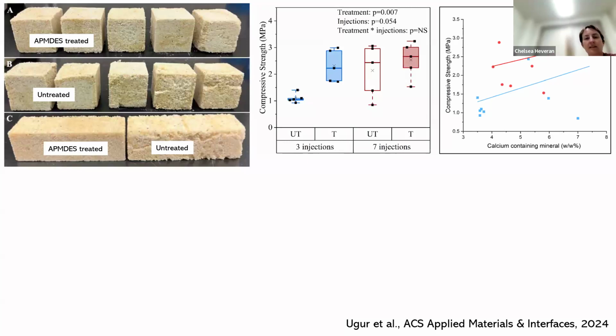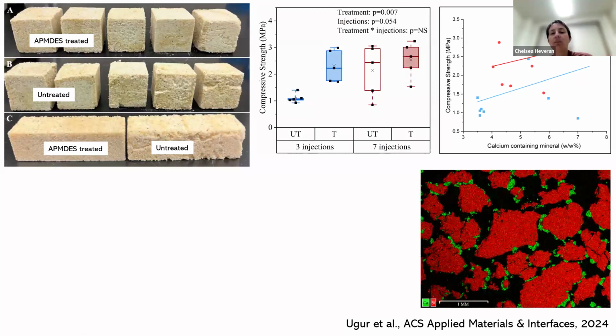And we see that reflected in our strength gain as well. So after 3 injections, our strength gain is really considerably higher than for our untreated specimens. And it takes those untreated specimens a long time, out towards 7 injections, to catch up. Importantly, the results are not just described by how much calcium was in the structure, which tells us that there's other attributes at play too.